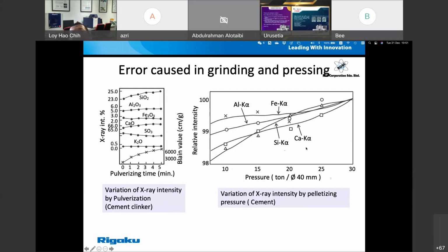And on the other graph, here is the effect of the pressure, the tonnage. If your pressure is too low, then you can see that your X-ray intensity is much lower. And as you increase the pressure, let's say for the silica, you achieve the intensity at a certain stage. Okay, this is why we say it's very important to have consistency. So when you press your samples today at 20 tons, you need to repeat the 20 ton process in the future. Don't say today I press at 20 ton, then tomorrow I press at 10 ton. You can see there's quite a big difference in the intensity. Okay, so this is very important.